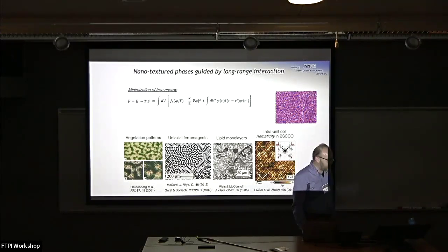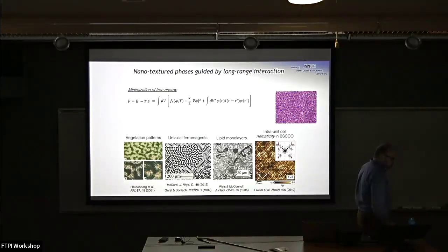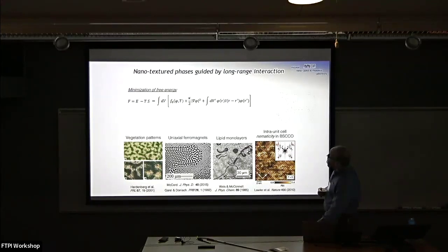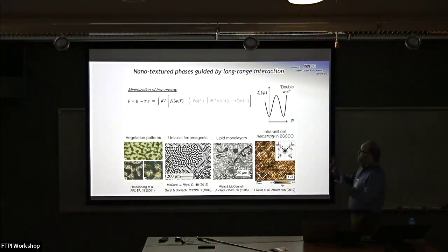Minimize that free energy. And to put a little bit more Landau theory into this section, let me just describe in terms of some order parameter phi what the energy looks like. And let me tell you what these different terms are in the energy density. Again, total cartoon, but one can apply it to each of these examples in some way. What might this free energy per unit volume be? A double well, if I'm talking about my first order phase transition. But we've got some local surface tension associated with the order parameter. We don't like to form domain walls. So it is the exchange stiffness, let's say, for a magnet.